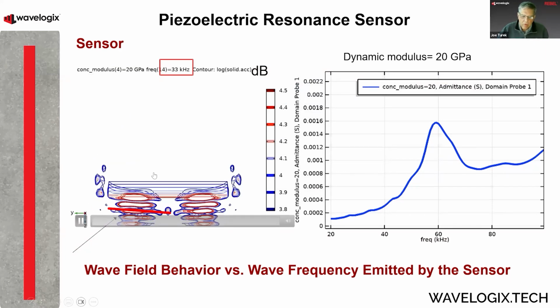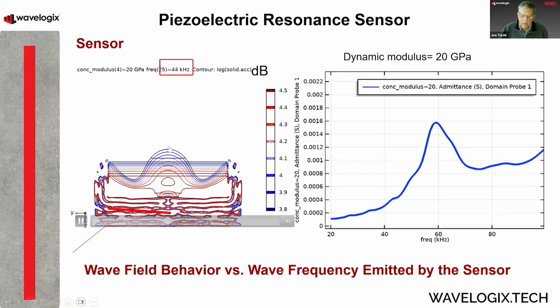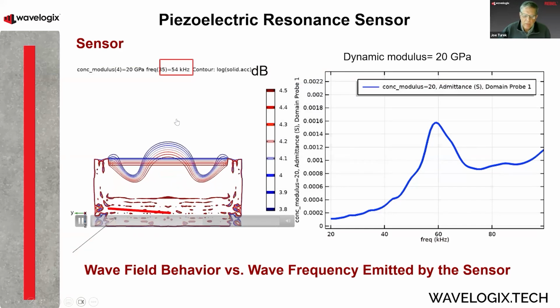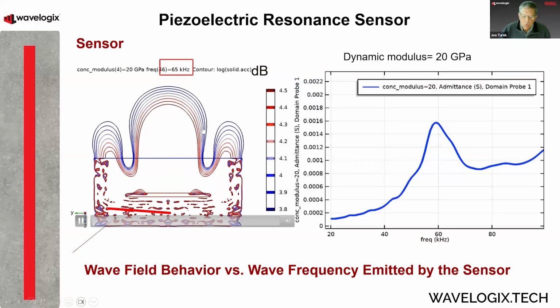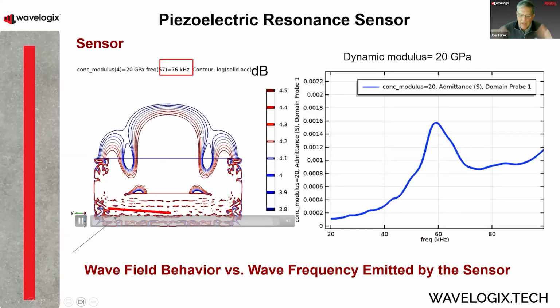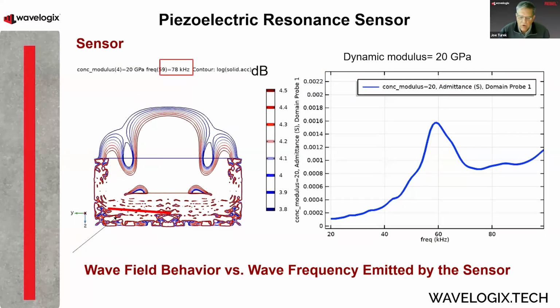So there's a lot of back pressure here on the wave. You can see the wave, it's getting this pressure. And when it hits that sweet spot, the resonant frequency, boom, now you get all this energy. You have no resistance or very little resistance, and you see that wave grow. If we plot that and we look at where the least resistance is for that wave, we can see a defined peak in that frequency. And we run the frequency from 20 hertz to 200,000 hertz. You're going to find that peak.